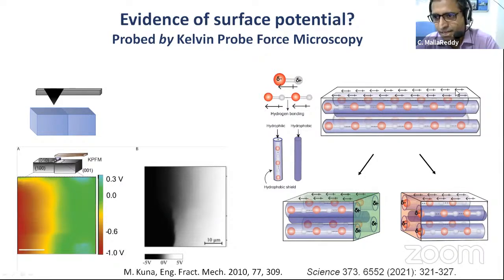So then you have polar direction. When you crack it, on one surface you have positive charge, on the other surface you have negative charge, because it is a kind of head-to-tail arrangement. This leads to the attraction of the pieces, and when they heal properly, you don't have remnant charges. So that is probably what makes them align properly.